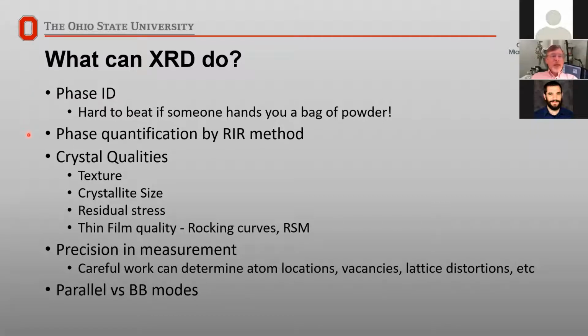And then as part of that, this qualitative identification, we can also quantify the amounts of the different phases that we have. As we're looking at these crystals that are in the crystal structure that we have in the material, we can start to look at the qualities. We can look at the size of the crystals. We can look at the texture or orientation dependence of the crystals. We can often see the residual stress that we have in crystals. And when we get to thin films, we can start to look at the quality of the thin films, as well as doing the same sort of phase identification.